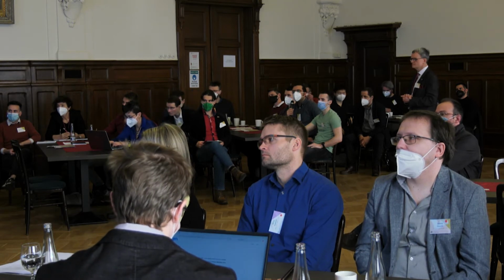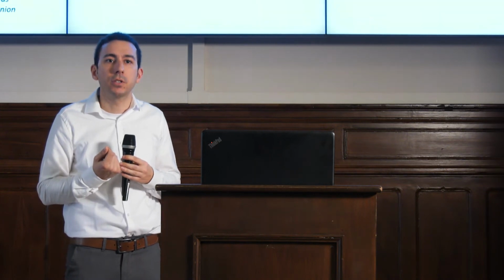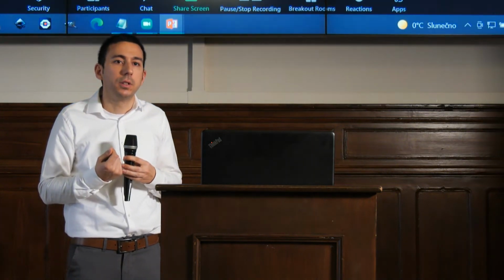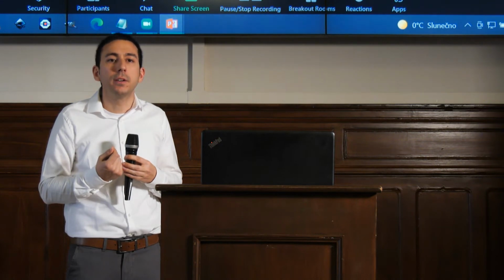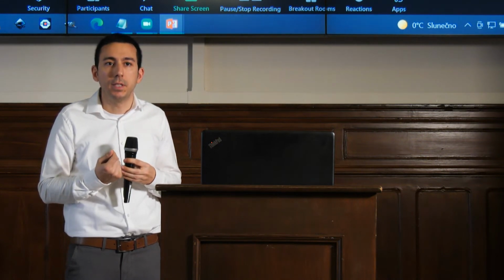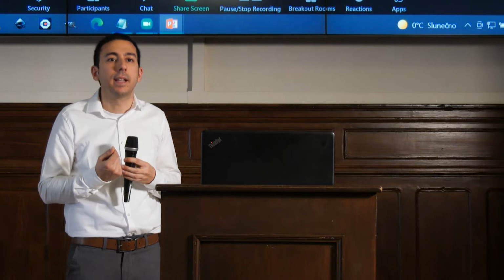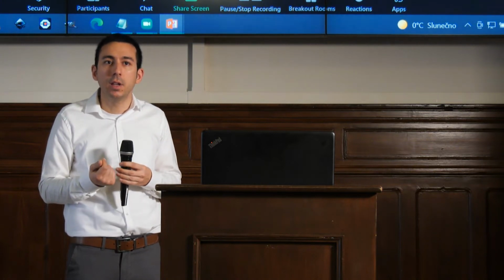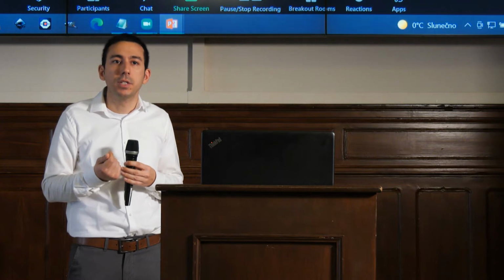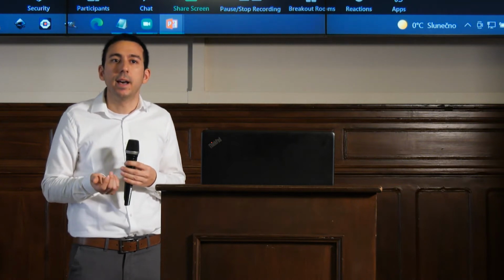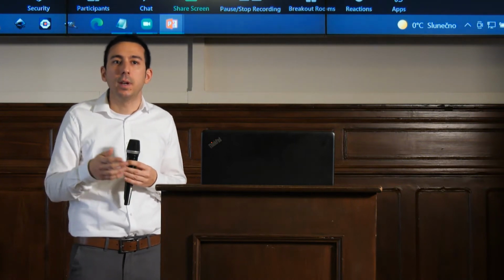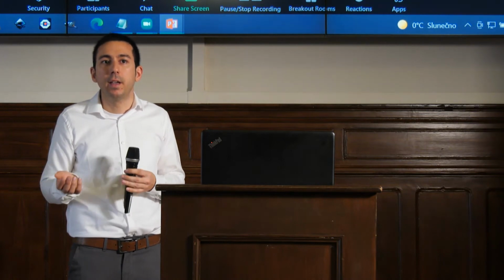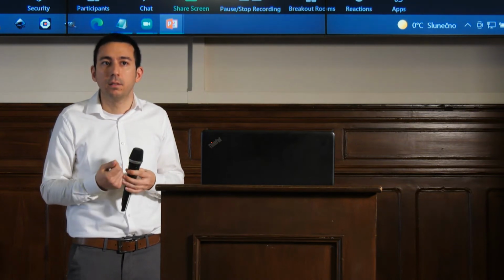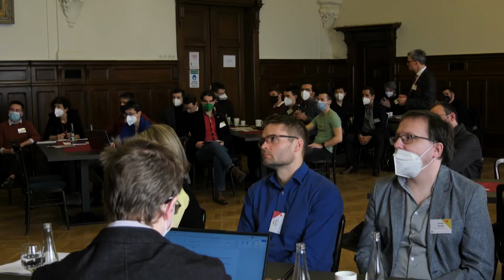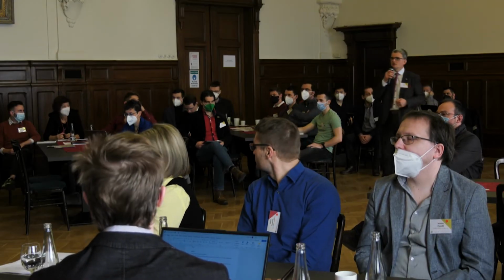In the case of the ferrocyanide, we don't see any change, or any change that we believe is promoted by the reactions of the ferrocyanide, because the protons are not involved in the redox equilibria of this species. What we may see is that if we have some unbalancing of the reaction and some permeation of oxygen, you can see some changes in the anolyte, and this can have an impact in the catholyte as well because of the compensation of the pH. Okay, thank you.